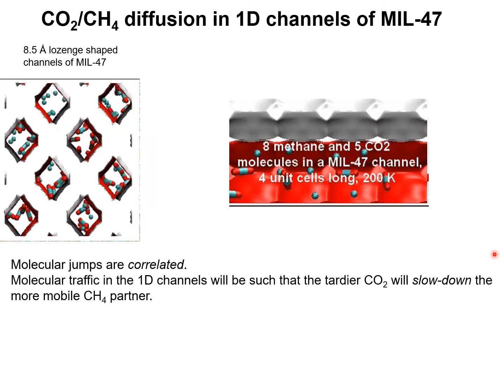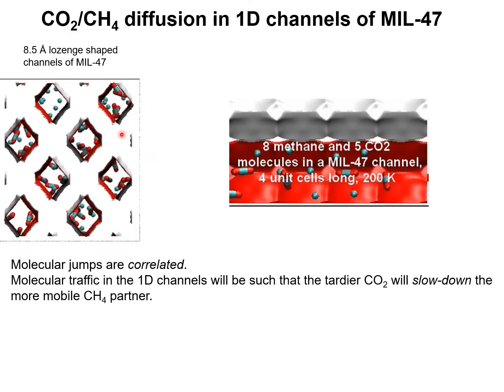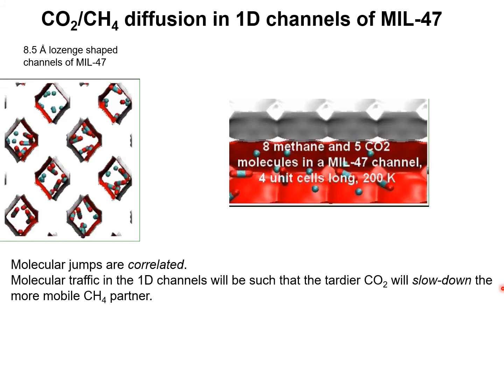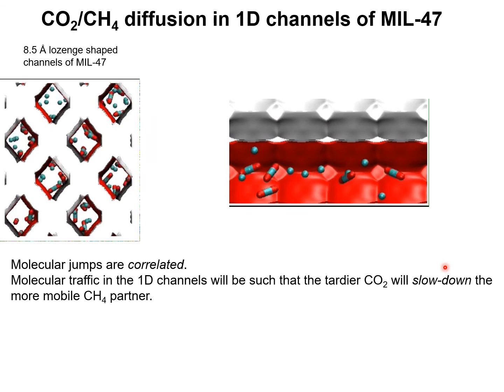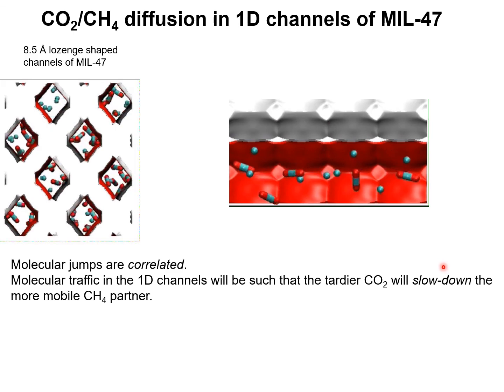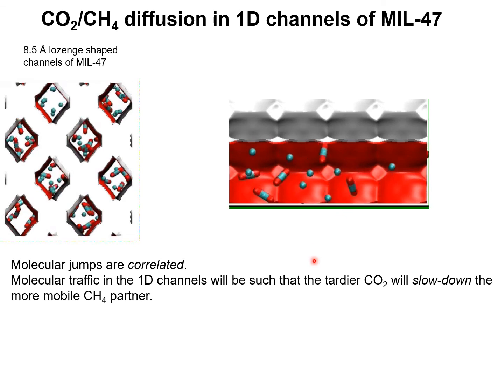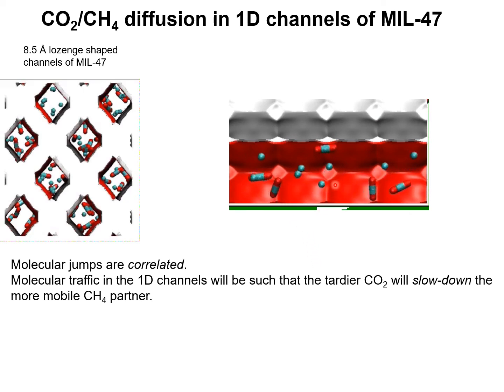For a mixture of carbon dioxide and methane diffusing within the 8.5 angstrom 1D channels of MIL-47, the most strongly adsorbed CO2 reduces the mobility of the more mobile partner. CO2 does not vacate the adsorption sites quickly enough for methane molecules to pass through the channels.